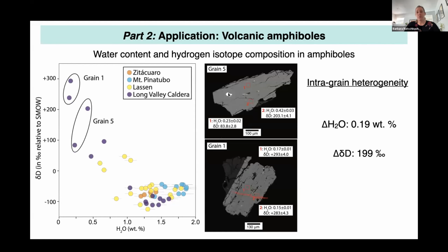So let's zoom into the data a little bit more and look at individual grains. Those are backscatter electron images of two grains from Long Valley. And you can see that within those two grains, there are big intragrain compositional heterogeneities in water and hydrogen isotope composition. So within a distance of 100 to 200 microns, we can see differences in water content of 0.19 wt.% and a difference in hydrogen isotope composition of about 200 per mil. And that's quite astonishing. That was quite unexpected. And that highlights again the necessity for high spatial resolution methods, and also implies that there are potential differences in ferric over total iron ratio in individual grains on a relatively small spatial scale.